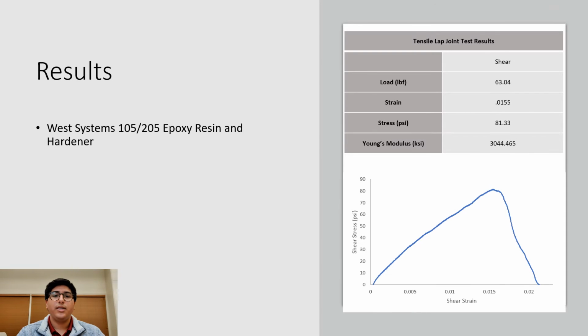The results of this test are what one would expect for an impregnating epoxy, which had a very low shear strength of only 81 psi. What's shown on the slide here is only the 170 degree cured sample, as it was the better of the two. From what we can see in the graph, the final result was actually extremely flexible and gummy, and the machine didn't even recognize that the bond had failed and therefore ran until there was zero stress measured.